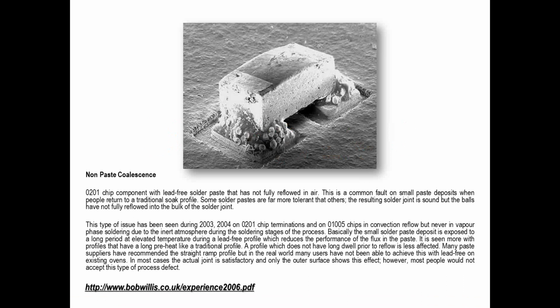Now, non-coalescence of solder paste, or what generally in America is called graping. And this is where we've either run a low residue paste in an air environment and we've exhausted the natural fluxing medium or the material available to aid reflow. And that's probably the most common reason for this particular process issue when lead-free was first introduced. A lot of people were trying to run profiles which weren't perhaps appropriate.